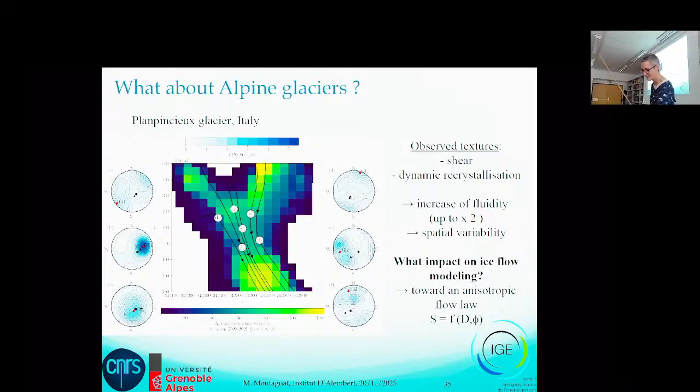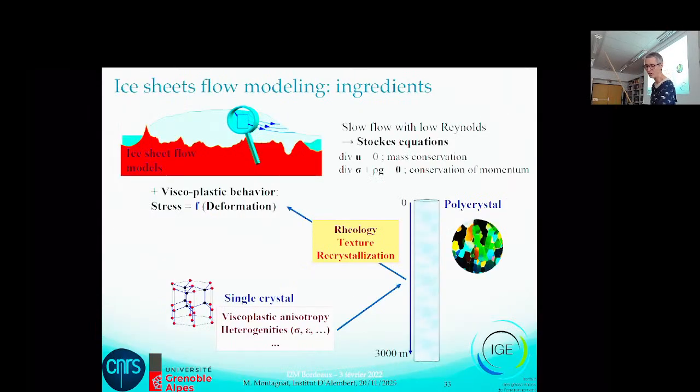So Glen's law is a law that comes from some experiments made by Glen in 1950, 52, 55, or this area. Glen took some polycrystals of ice, made some creep experiments, just put a load on top of it, and he measured the creep curve.